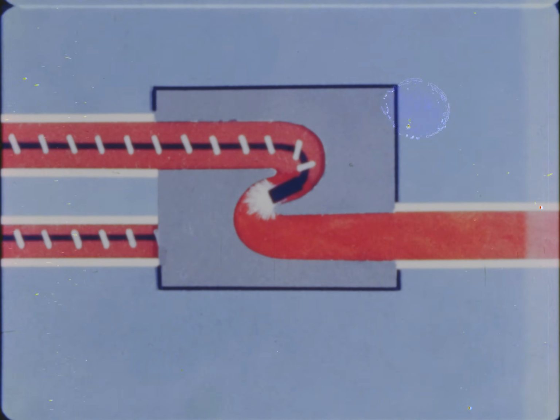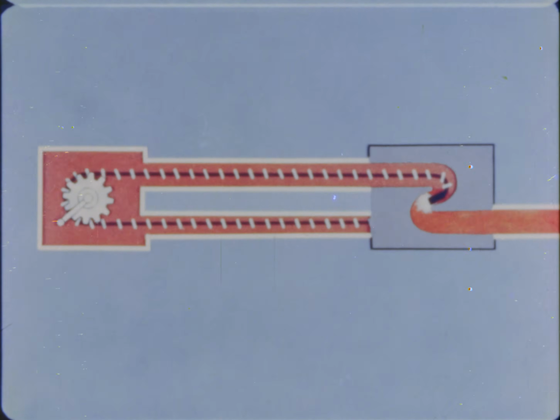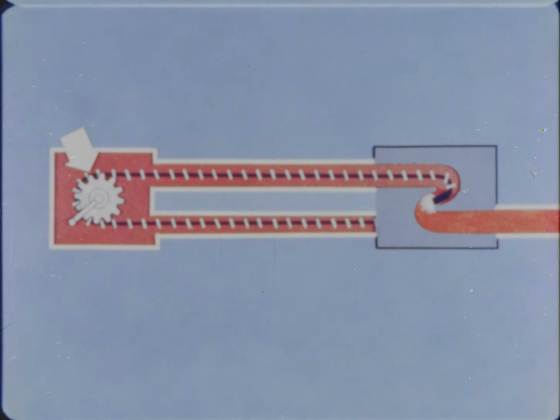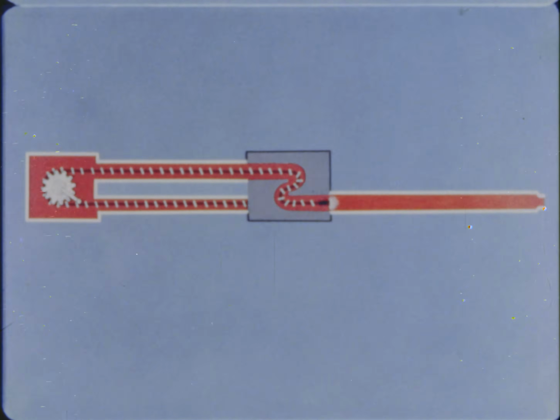A different type of isotope application is radiography. Isotope radiography units consist of a shielded housing for the stronger source and a means of unshielding the source for use. When the object to be radiographed is in position, with the film behind it, the source is unmasked. Film blackening is inversely proportional to ray absorption in the material and interior flaws. Voids or discontinuities appear as darker areas on the developed film.